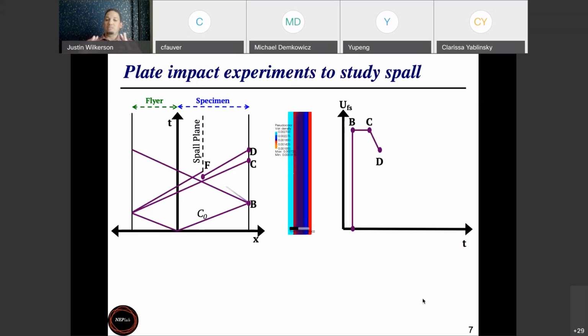And then the opposite happens in tension. So in tension, the bulk modulus will decrease as you stretch the material because you're taking the atoms and spreading them farther apart. So how that plays into waves is that the wave speed is the square root of the stiffness divided by the density of the material. So if the stiffness of the material is increasing as you're compressing it, then every time I increase to more and more compressive stress, the bulk modulus is going up, so the wave speed is going up.